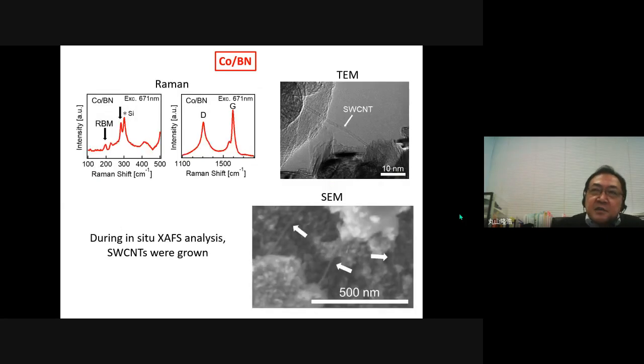After in-situ XAFS analysis, we performed Raman, TEM, and SEM to confirm nanotube growth. In Raman spectra, both RBM peaks and G-band peaks were observed, and TEM observation also confirmed growth of single-wall carbon nanotubes. So we confirmed that during in-situ XAFS analysis, single-wall carbon nanotubes were grown. Next slide, please.